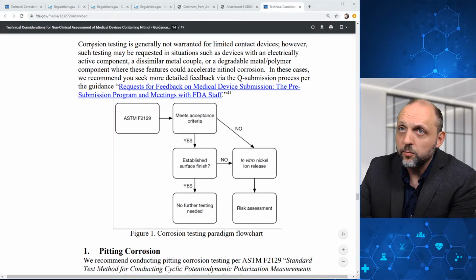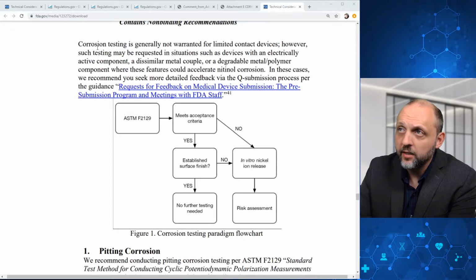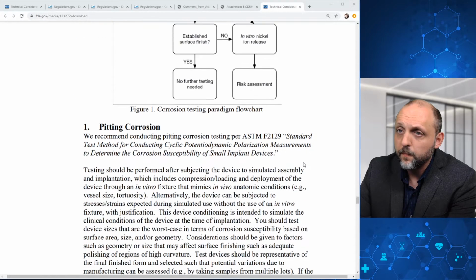And here FDA specifically calls out that corrosion testing is generally not warranted for limited contact devices. However, such testing may be requested in situations such as devices with an electrically active component, a dissimilar metal couple, or a degradable metal polymer component, where these features could accelerate nitinol corrosion. And again, FDA references the Q-sub process here.